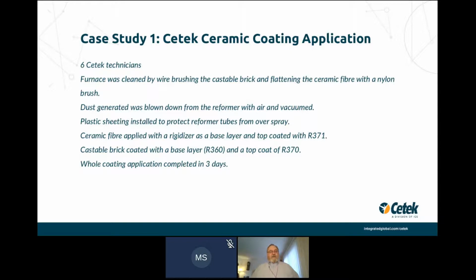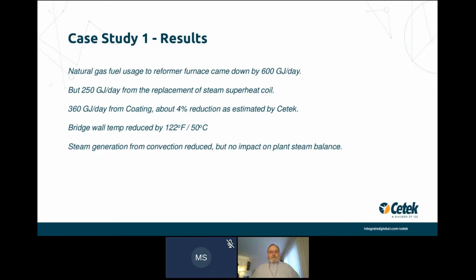The ceramic fiber, we apply a rigidizer first, and then we put an R371 coating on top. And the brick was coated with a base layer of R360 and then a top coat of R370. These are typical materials that we use in refractory linings in high temperature units. The whole coating application, we occupied the unit for 3 days. So the results, you'll see there that